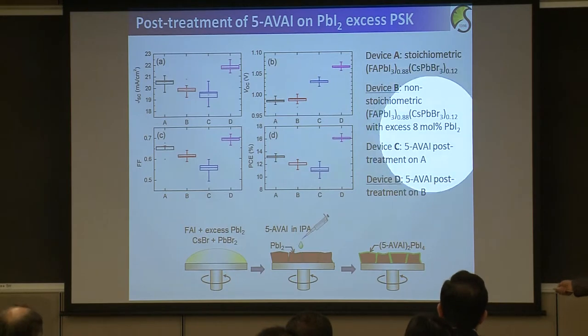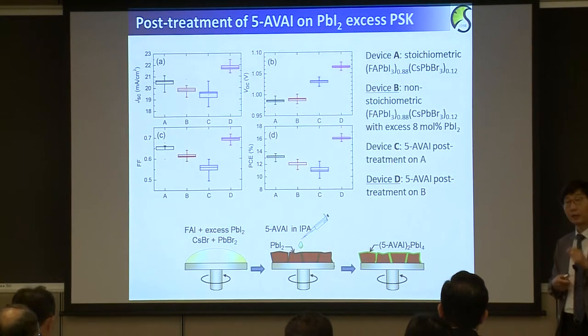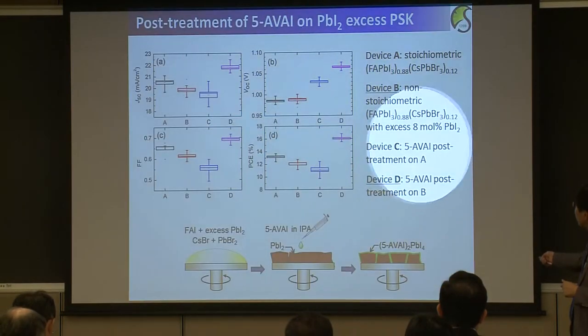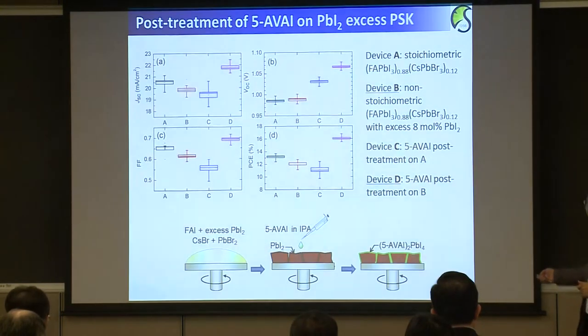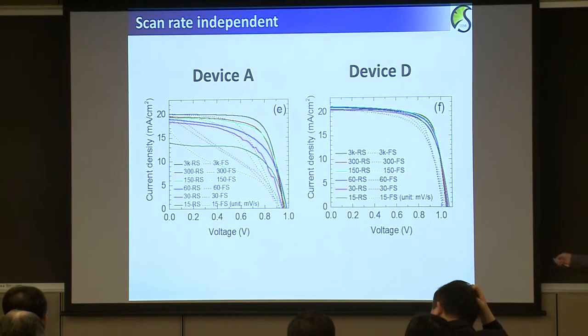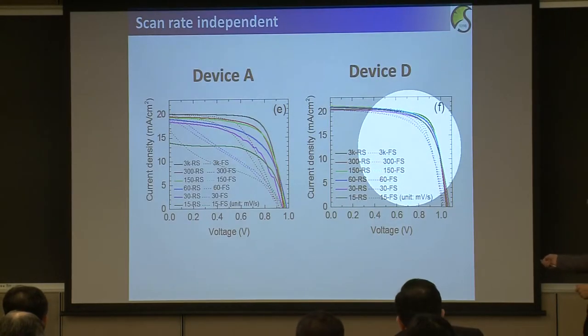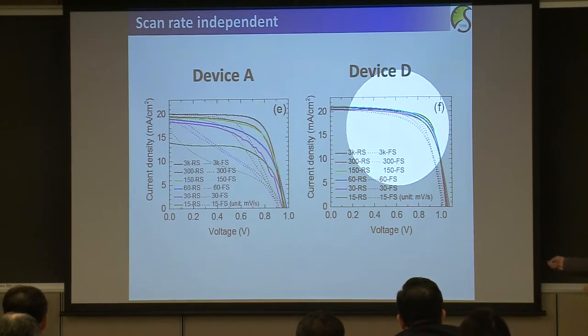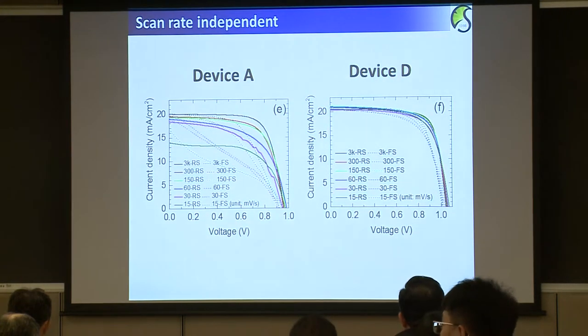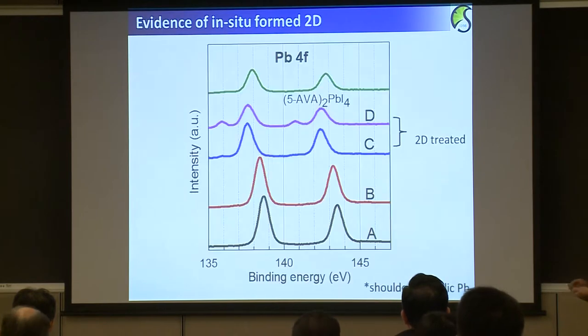And because this is a very good process, you can control the thickness of the two-dimensional layer by modifying the concentration of PbI2, okay? And then we found that the hysteresis is greatly reduced after introduction of the two-dimensional layer in between copper thiocyanate and perovskite, as compared to the huge hysteresis without the two-dimensional layer.